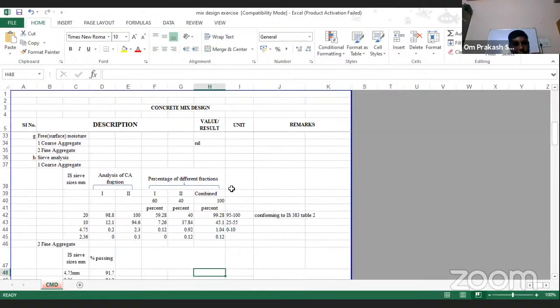Now, here is my sieve analysis. From the left hand side, 20, 10, 4.75 and 2.36. First one is the sieve analysis of 20 mm aggregate, which is 98.8, 12.1, 0.2 and 0. And the second one is the sieve analysis of 10 mm aggregate, that is 100, 94.6, 2.3, 0.3. Here the proportion I have taken is 60-40. So their combined grading is coming 99.28, 45.1, 1.04 and 0.12.